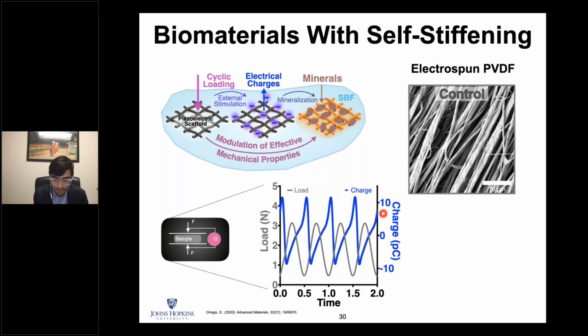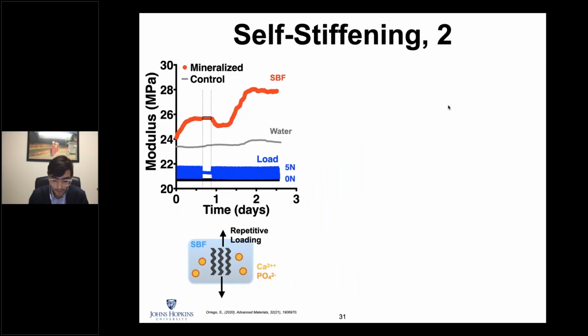The first thing we did, as usual, is measure the amount of load with the grade, then measure the amount of charge to show that indeed these scaffolds were producing charge. And then we monitored the modulus change with time.